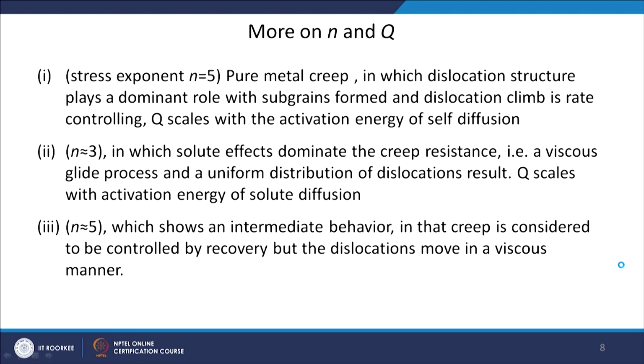A stress exponent of around 5 is usually what you will see in pure metal creep, in which the dislocation structure plays a dominant role, with subgrains formed and dislocation climb being rate controlling. So dislocation creep takes place at relatively higher stresses, as also happens during hot deformation. Dislocations will be generated, and they will realign and rearrange through climbing into subgrains forming low angle grain boundaries, and they get recovered through this rearrangement. Dislocation climb is the rate controlling process.